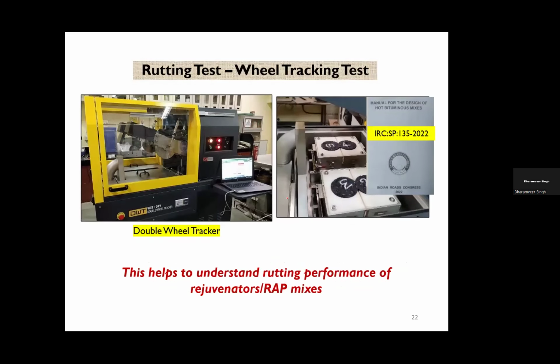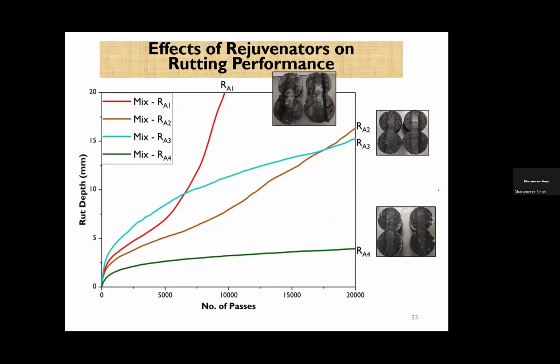Another thing is the rutting value, and I will show you very interesting findings on the rating. You have different rejuvenators, for example rejuvenator 1, 2, 3, and 4, and all are well established. They are all claimed to be very good rejuvenators. You have decreased the viscosity, your job is over. However, when you go to the long-term performance of the mix, you see a different result altogether. All the rejuvenators were very good in the beginning and showed excellent results. However, when you do the performance test, you realize that rejuvenator 1 is going to backfire. It may make your mix so soft that it will rut 100% within no period of time. And if you use rejuvenator number 4, you will see it provides better performance and rutting is less of an issue.